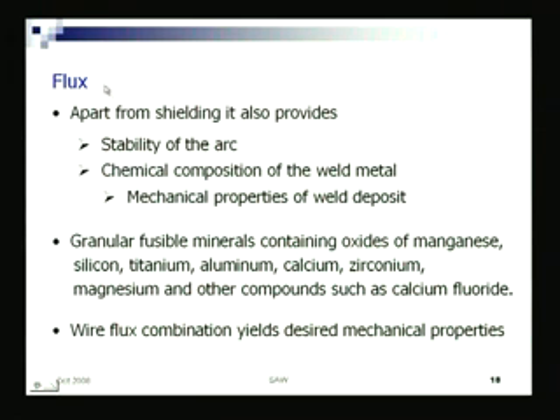Now the type of flux, apart from shielding, affects the stability of the arc, and the chemical composition of the flux affects the mechanical properties of the deposit. This flux is basically made up of oxides of manganese, silicon, titanium, aluminium, and others. It is essentially a mixture of all those oxides.